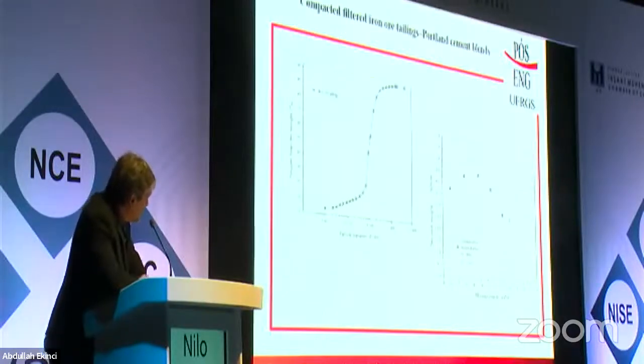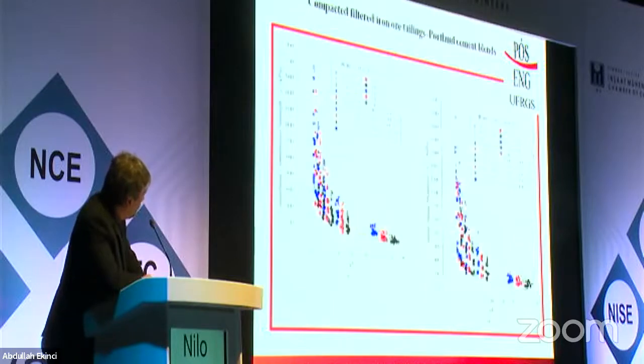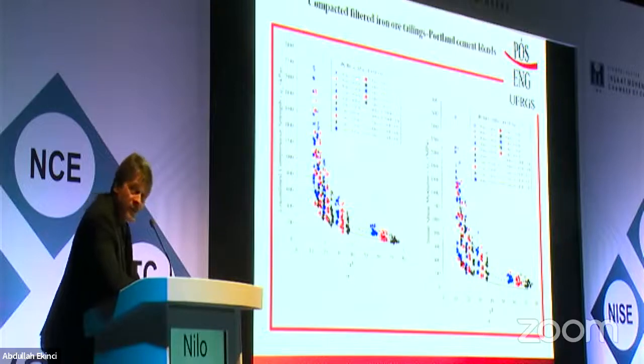So this is a paper that I'm bringing back from previews that was published at the beginning of this year, in which we have shown, here is a kind of, not a good picture, but we have here curing periods from 2 days to 90 days. And also we have 3 different dry densities used, and we have a fit for each and every curing time, and they show the same curvature. The only thing that changes is the scale in front of the equation.